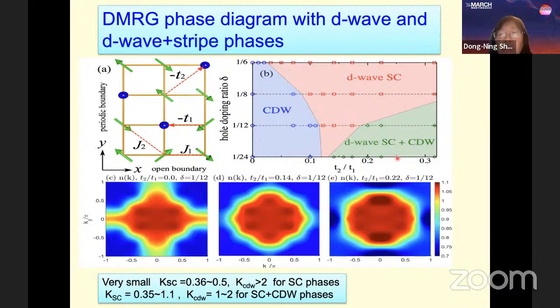If we fix the parameter T2 over T1, then we can have the transition from CDW to D-wave superconductivity, or from the coexisting phase to D-wave superconductivity. In other words, the superconductivity always becomes more robust as we move towards optimal doping.